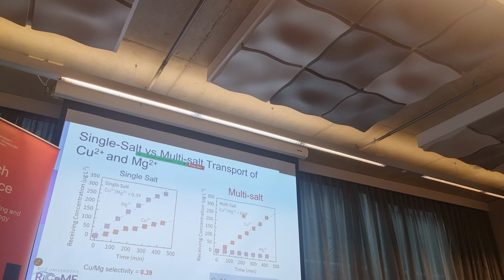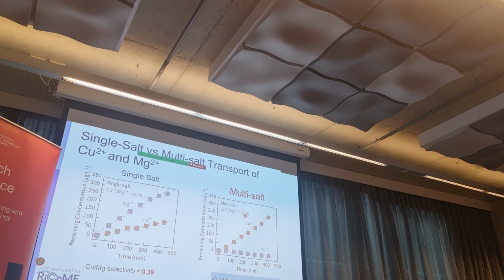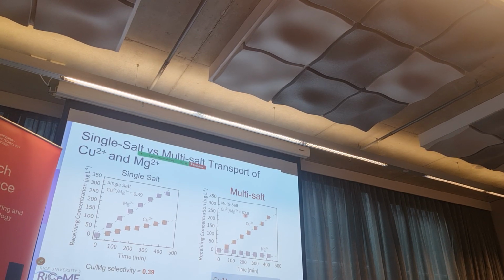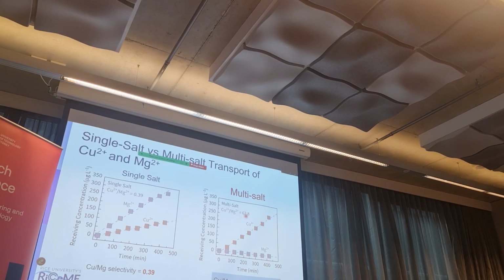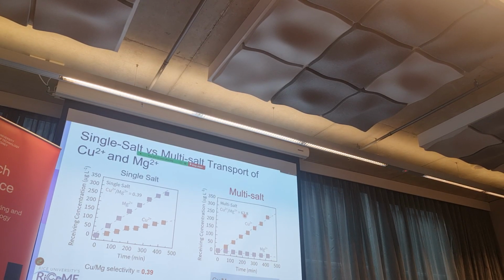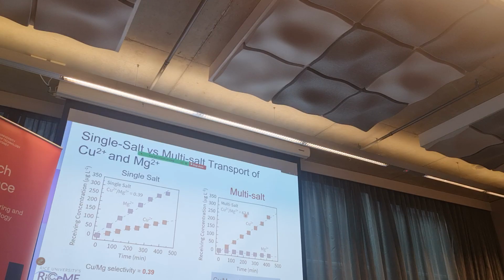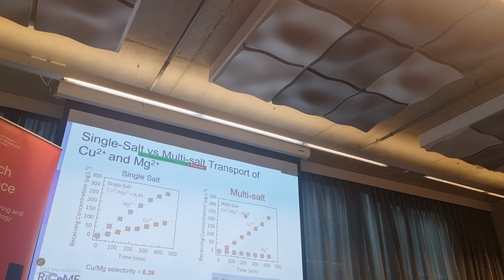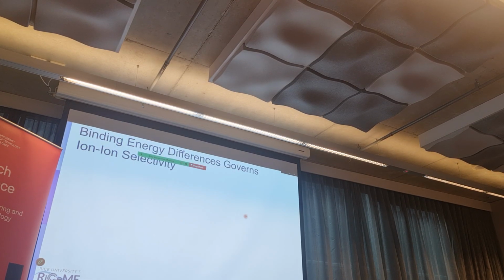This shows that if you have the right binding site, you can achieve high selectivity. But since we use a layer-by-layer membrane, we can't control the exact site distance or pore size. If you could do this with uniform channels and very controlled modification, you could get even higher selectivity.